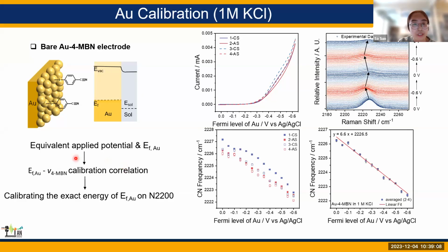So basically, if we have the correlation between the Fermi level of gold and the nitrile frequency, we can use the nitrile frequency that we observed from the N2200 case to backtrack the exact energy of the Fermi level of gold on N2200. It's a little complicated to say, but I think it will be clear when I show the data. So basically, for the calibration correlation experiment, I scanned the gold between 0 to negative 0.6 volts for 2 times of cathodic and anodic scan.